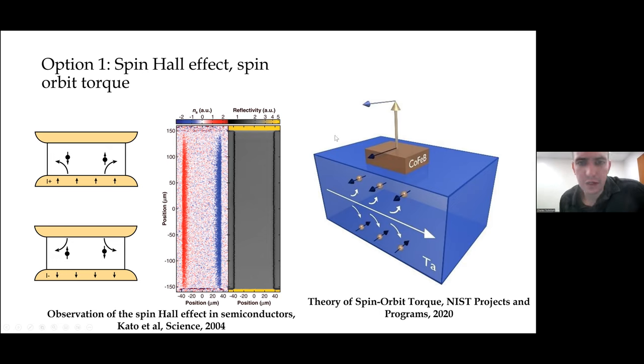And there's a cottage industry of using this phenomenon, the accumulation of spin on opposite sides of the device in response to a transport current in the presence of strong Berry curvature, to realize magnetic bits. So what I'm showing at right is what's known as a spin orbit torque bit. Electrons are flowing through the tantalum, which has this spin Hall effect. Electrons of opposite spin flow to different sides of the device, and a magnet has been attached to one side of the device, and it can be flipped with this local enrichment in the spin population.